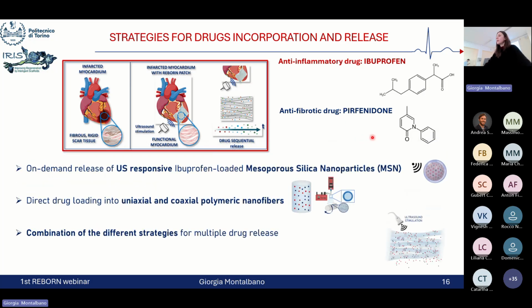So the incorporation of these drugs into the final patch was explored using different strategies. Here we have just listed the most effective ones that were related to the design of ultrasound responsive carriers loading the anti-inflammatory drug ibuprofen, but also in parallel we explored the effective incorporation of the drugs and the simultaneous release of them using uniaxial and coaxial polymeric nanofibers, so just directly incorporating the drugs into our polymeric formulation. And then the different successful strategies were combined in order to enable the multiple drug release from the final patch.